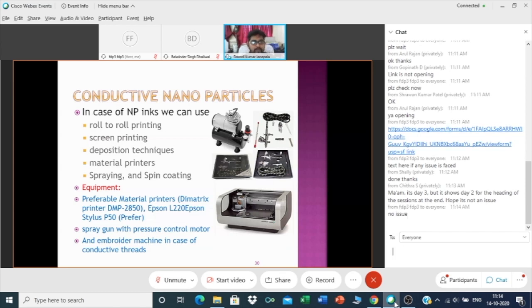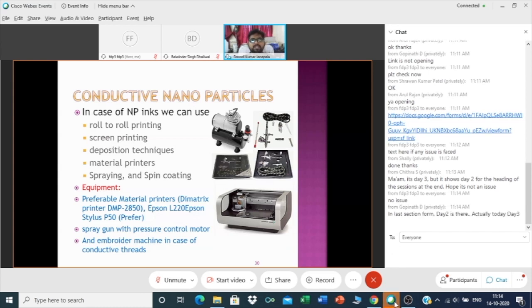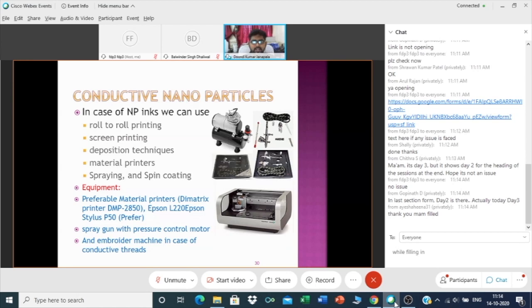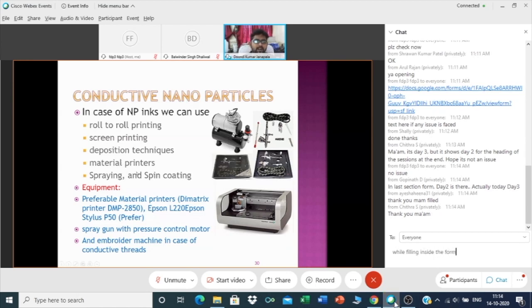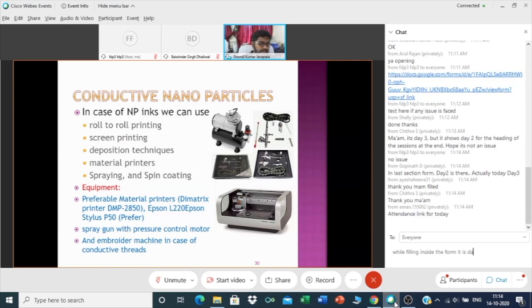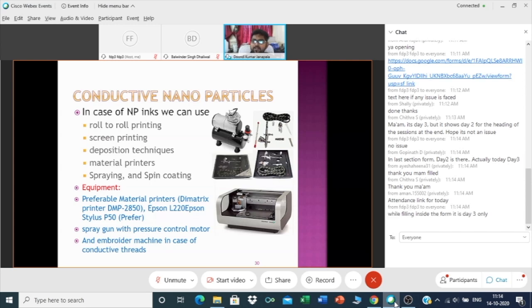Make sure your polymer is activated properly, and when you are spraying, it's better you take your polymer in a preheated condition, probably 60 degrees or a little bit above. Why I'm saying preheated is, most of the inks that we take, we will mix it with isopropyl alcohol along with our particular nanoparticle.